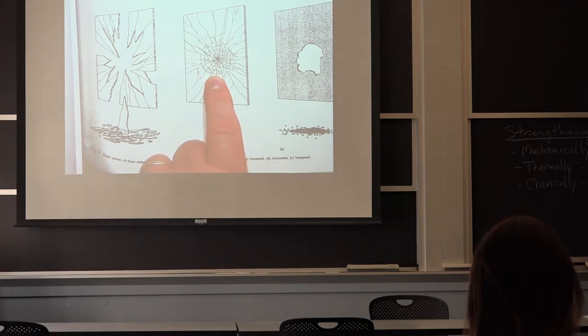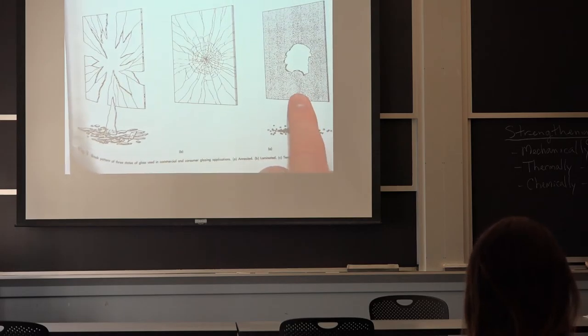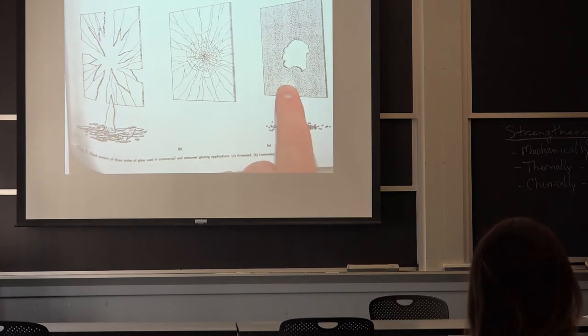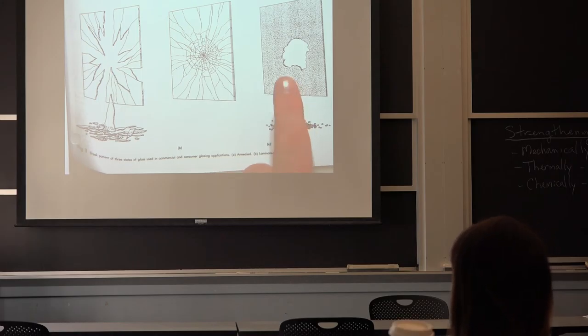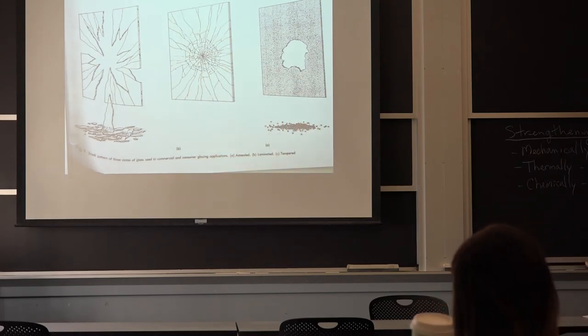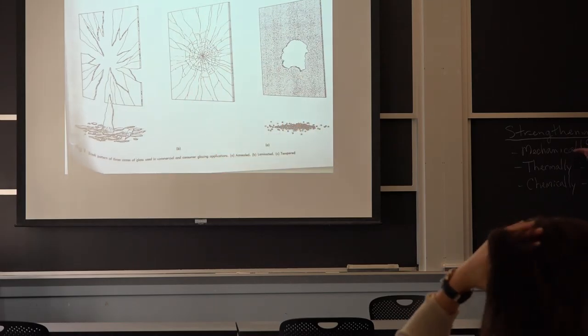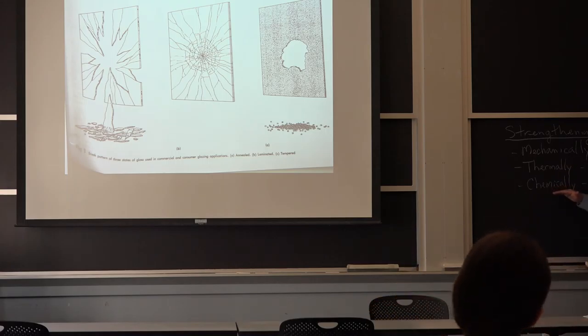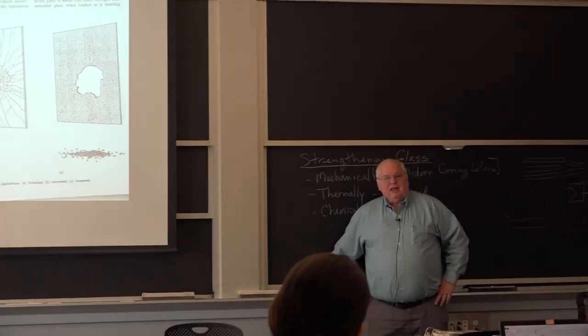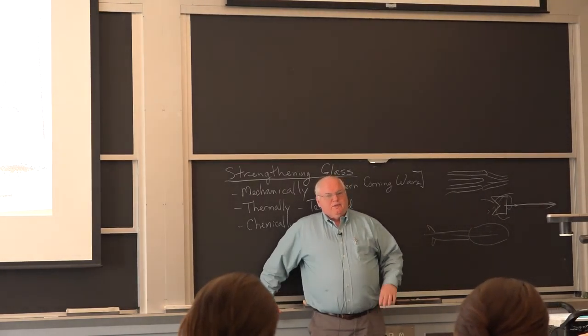You don't want shards of glass hitting the person in the face. Even tempered glass could be unsafe at 60 miles an hour if it breaks suddenly, right, in your face. But along the side windows, where it's less likely, they use tempered glass, cheaper than laminated glass. So we have different ways mechanically and thermally to strengthen the glass. We also have a way of chemically strengthening the glass.